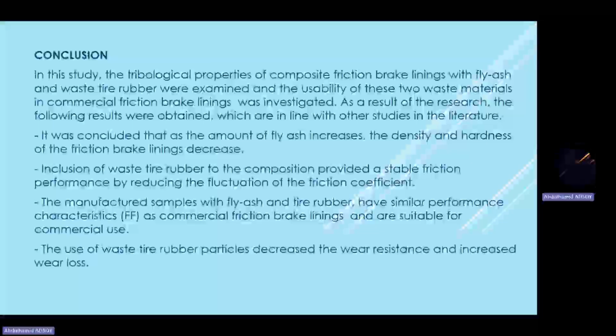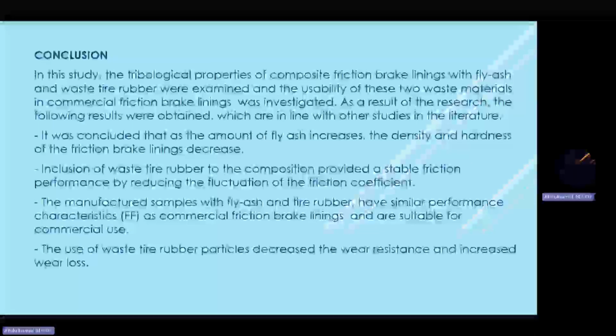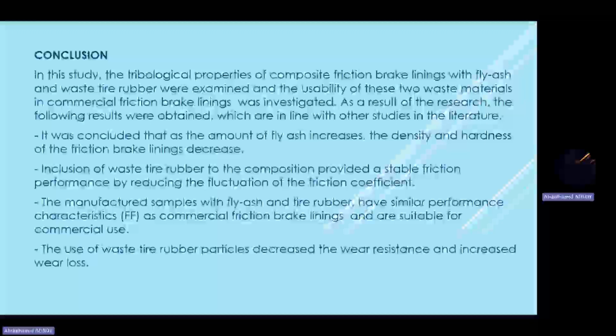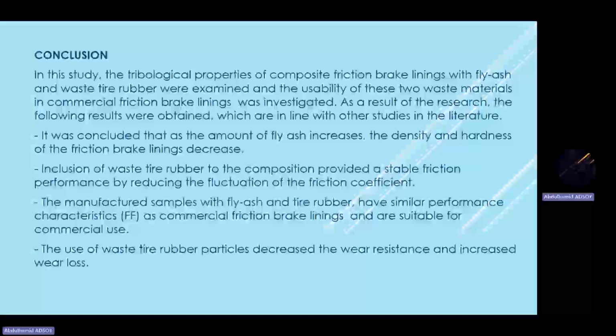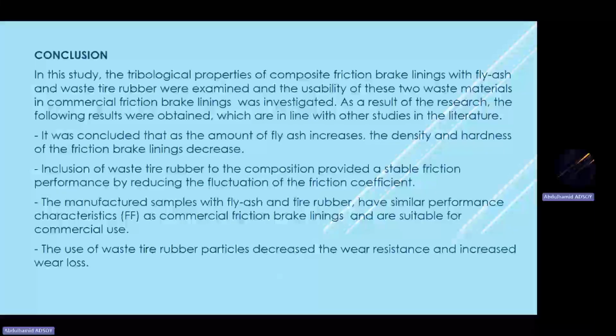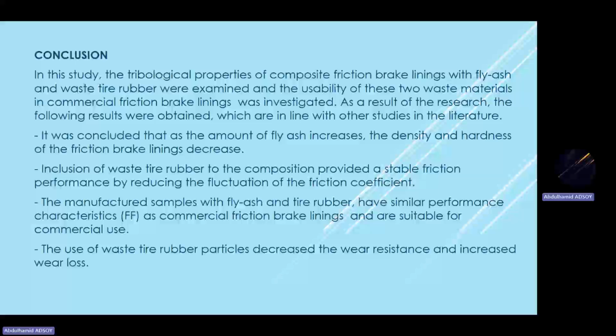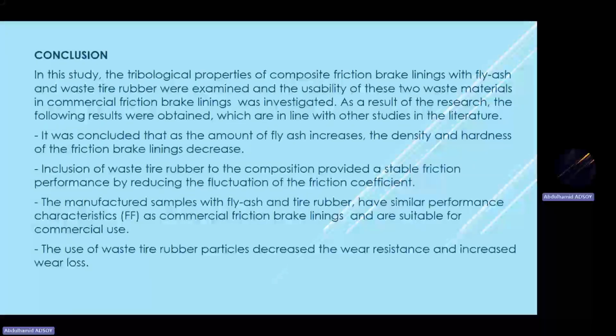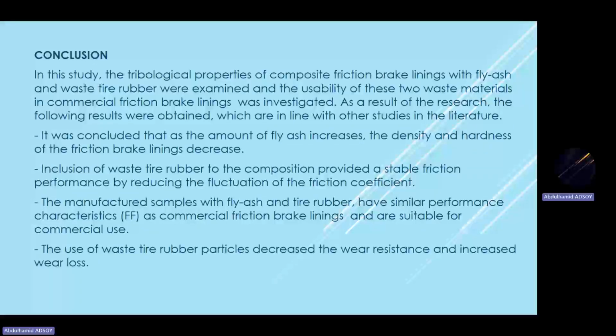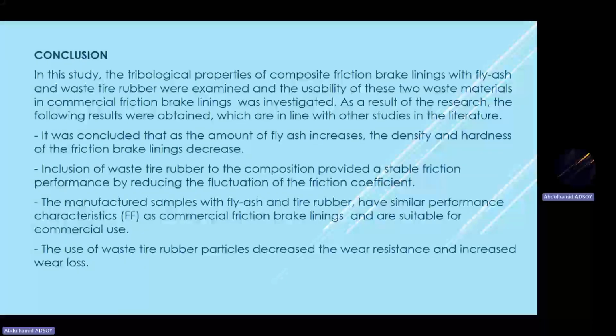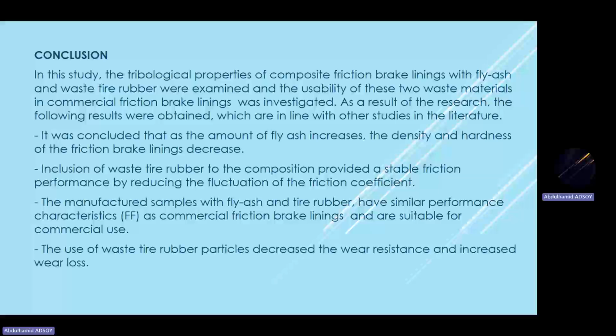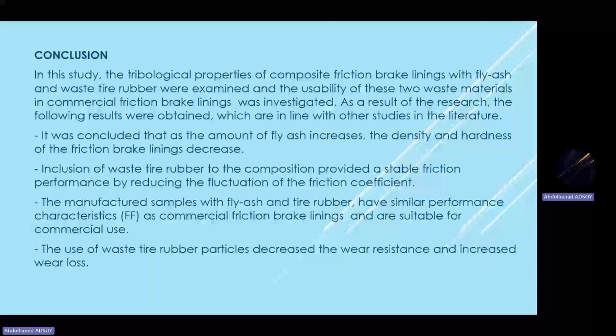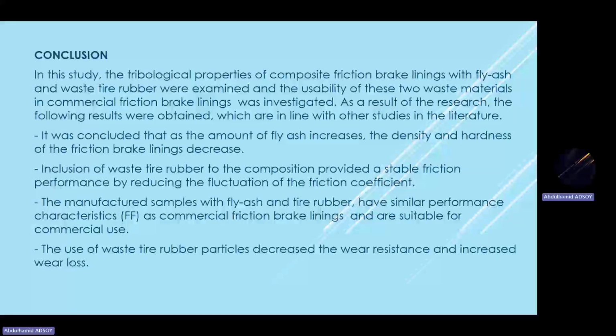Now, in this study, as a conclusion, the tribological properties of composite friction brake linings with fly ash and waste tire rubber were examined, and the usability of these two waste materials in commercial friction brake linings was investigated. As a result of the research, the following results were obtained, which are in line with other studies in the literature. It was concluded that as the amount of fly ash increases, the density and hardness of the friction brake lining decreases.